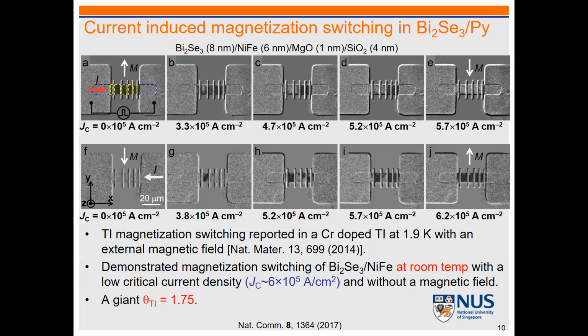Then we put the nickel iron on top. Then we chop the nickel iron into small squares. If you look at this microscope image from the top view, each yellow square is one nickel iron stripe. We pattern with different sizes because we want to change anisotropy and so on and see what happens. Once you inject charge current from the left electrode, all the black domain indicates it is saturated in this direction, but you can see some white domain is enlarged, and eventually you can switch everything to white, meaning now it's pointing in the opposite direction.